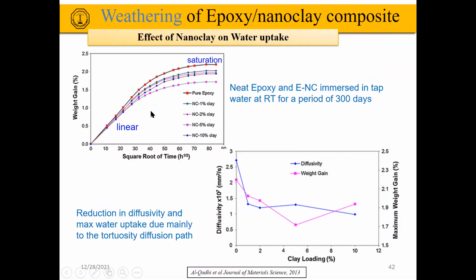We started looking at how the water uptake is affected by the presence of nanoclays. We looked at the percent weight gain as a function of the square root of time in hours. And you can see that the red squares here are for pure epoxy. This is about 300 days of exposure. The weight increases by 2%, 2.3%.